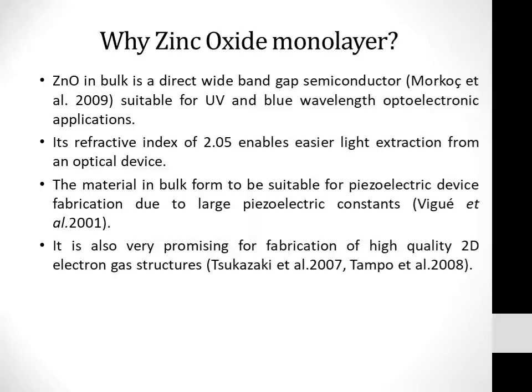Studies also show ZnO has a large piezoelectric constant, resulting in strong piezoelectric polarization in the material, making the bulk form suitable for piezoelectric device fabrication, and very promising for fabrication of high quality 2D electron gas structures. What is a 2D electron gas structure? It is a scientific model in solid state physics. It is an electron gas free to move in two dimensions but restricted in the third dimension. It has many useful and interesting properties.